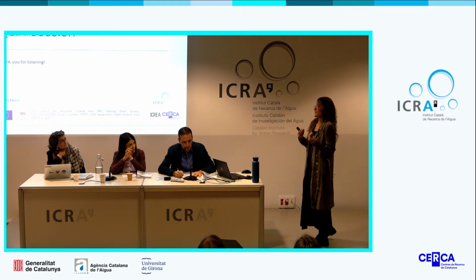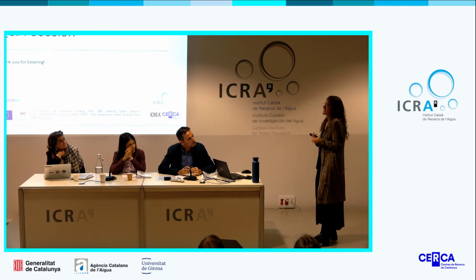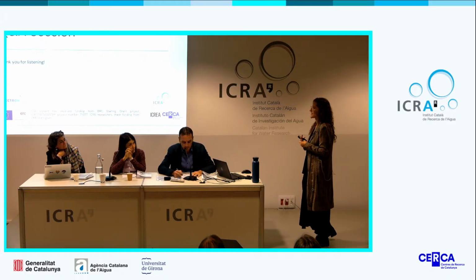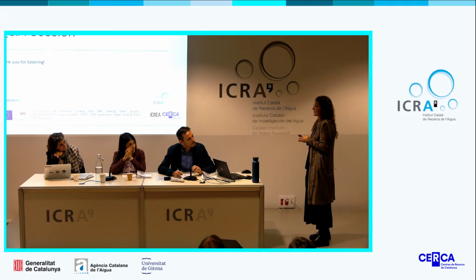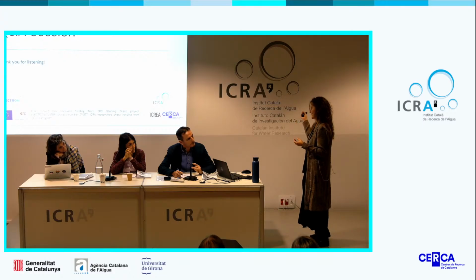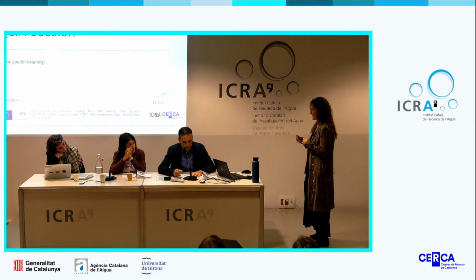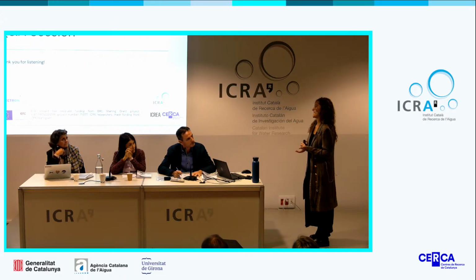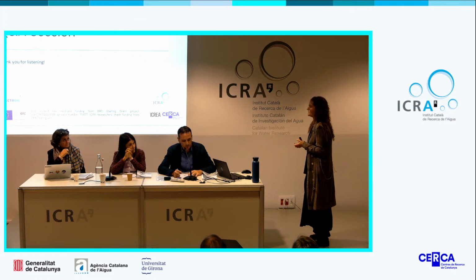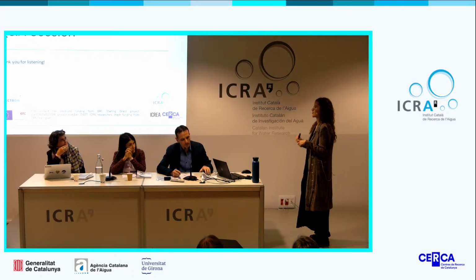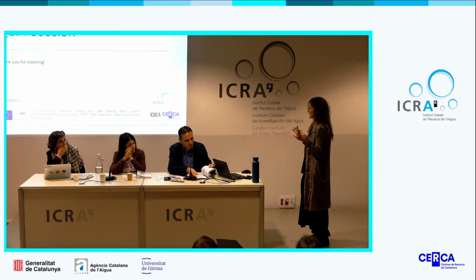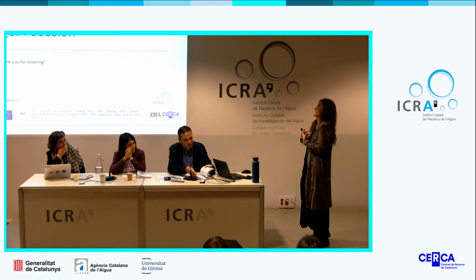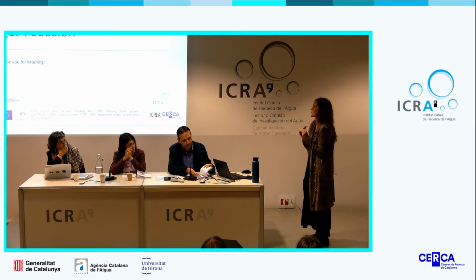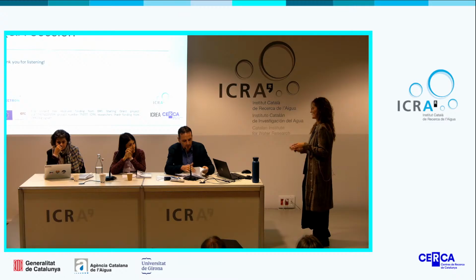The participation of the oxidant species is more difficult to assess. I will say that they are partially participating because, for example, in the two sequential reactors I was explaining that since an increase of the current didn't enhance the concentration of oxidant species, probably the major mechanism is electroporation instead of oxidant species. But we cannot confirm which percentage of participation is in both cases.